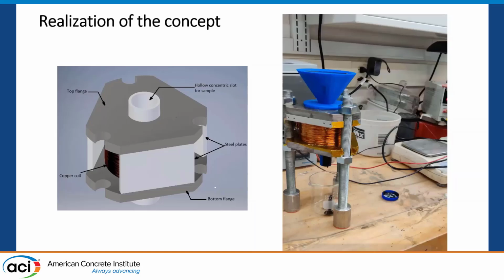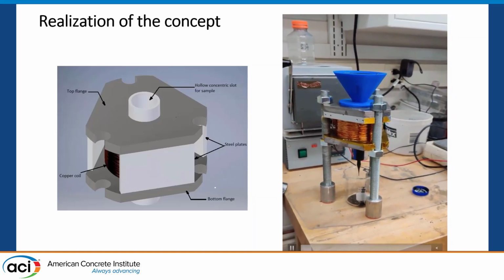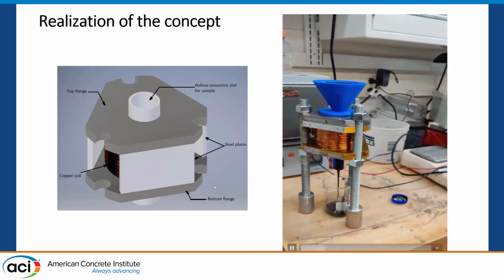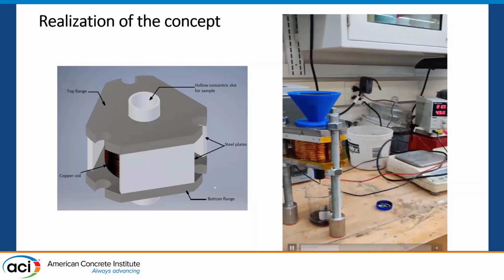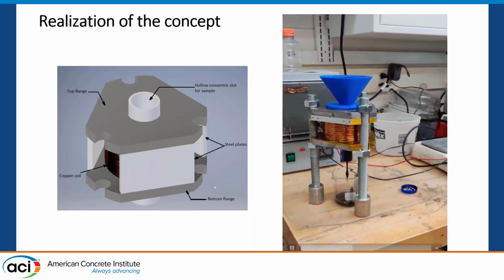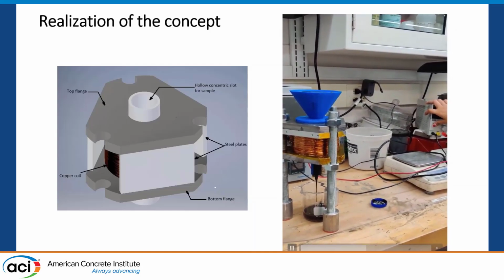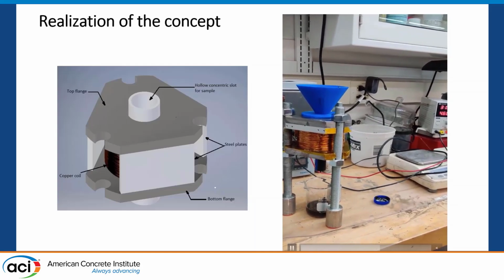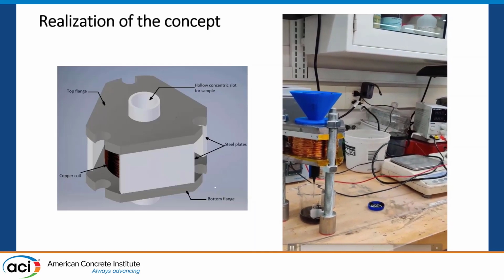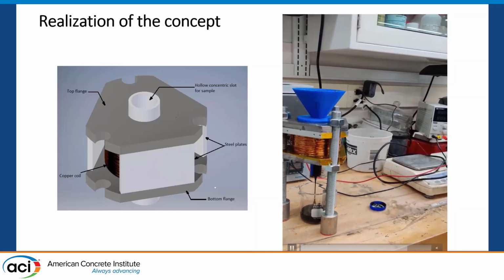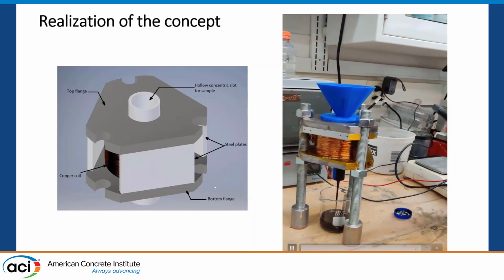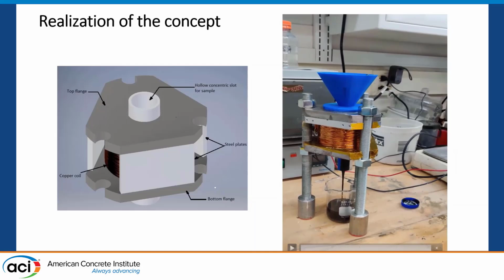So it was one of our first experiments to test the concept. I don't know if it runs. So basically, you see you have a funnel with, I believe, an 8 or 10 millimeter opening, and you have the power supply on the right, and the student is switching the electrical field on, and now it's off, and so the material starts to flow. Pay attention that you have first chunks of material which was magnetized, in the capillary, and as soon as it runs, you have free flow. The funnel is full, so you have enough material, enough pressure for the material to flow. But obviously, these chunks are magnetized material. Now we have free flow of the material through the funnel. And again, this was one of the first experiments to demonstrate the concept and basically use this setup as a magnetic valve.